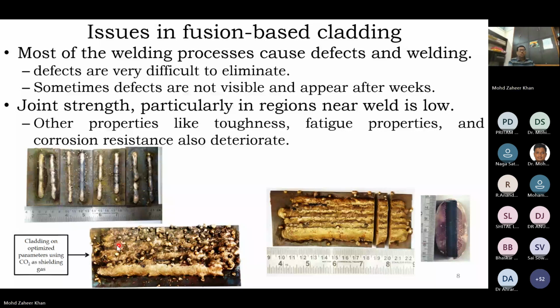like this. When we were using carbon dioxide as the shielding gas, a lot of spatter was coming. When argon was used as a shielding gas, there was a serious problem of arc stability. The arc was getting extinguished. So, a specific composition of shielding gas consisting of argon and CO2 was supplied, and with somewhat less spattering, we could deposit several intersecting layers of copper on top of the substrate, so that the mild steel substrate could be completely covered with a layer of copper.